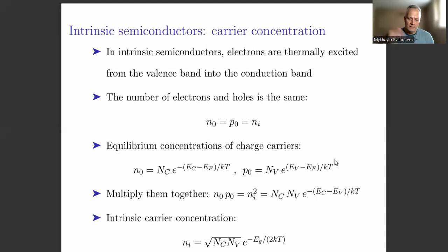Again, because exponential to the power 2.3 is 10, you want, in the Fermi-Dirac distribution, 1 divided by 1 plus exponential to the power energy minus Fermi energy over kT. As long as the Fermi energy is below the conduction band edge by at least 2.3 thermal energies and above the valence band edge by at least 2.3 thermal energies, you can use Boltzmann's approximation. And this is the validity range of the mass action law.